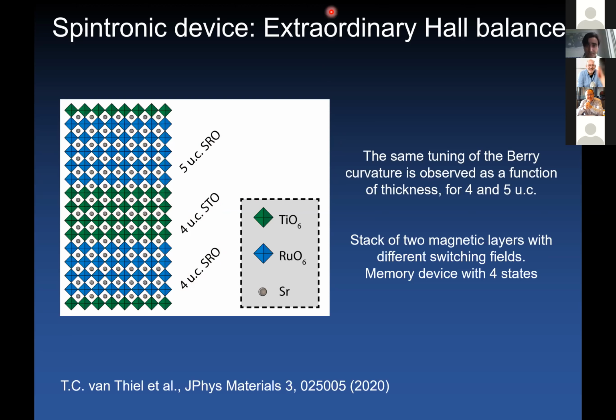We have a question. How from photoemission could they get the Berry curvature? Yes, good question. So from photoemission you measure the avoided level crossings, and from the avoided level crossings, then you can calculate the associated Berry curvature. But I agree with you. In photoemission, you don't measure directly the Berry curvature. Actually, Berry curvature is proportional to the off-diagonal component of the resistivity tensor. So a transport measurement is a more direct measurement of this phenomenon. Let's say the whole thing is nicely consistent though.